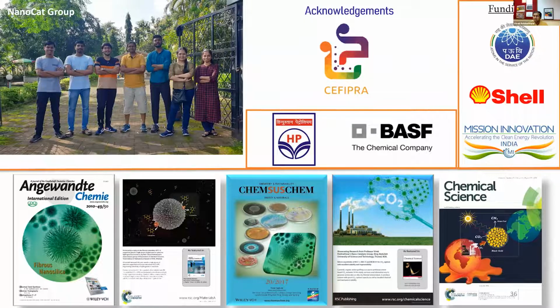Yes. So luckily here we did not tune any energy levels, because you get a different energy level based on what type of light wavelength you add, right? An electron can go to even higher and higher excited states. So some of them will definitely get transferred to the oxygen. In the oxygen case, it was a very efficient transfer. That's why we got a very good conversion, whereas the same electron was not getting transferred to the CO2.